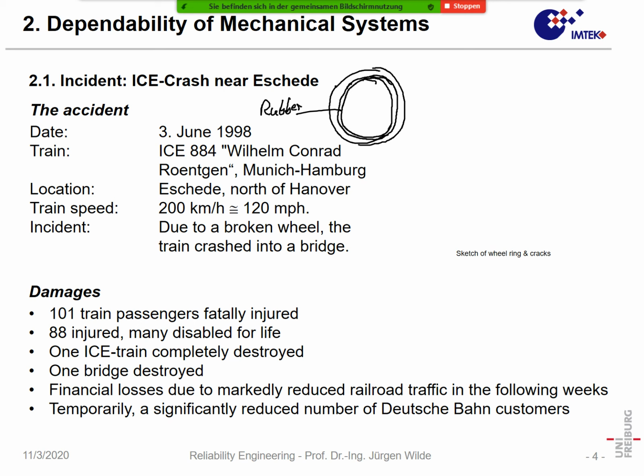Unfortunately, these rings get ripples, and in order to remove these ripples, they must be turned down. And the reason what happened and what led to the crash was the following. Here we had cracks which developed due to fatigue, and that weakened that ring. And on the other hand, by turning down the wheel over time, the ring became thinner and thinner, and at some point the ring was too thin and the fatigue crack was too long, and so this ring just broke.